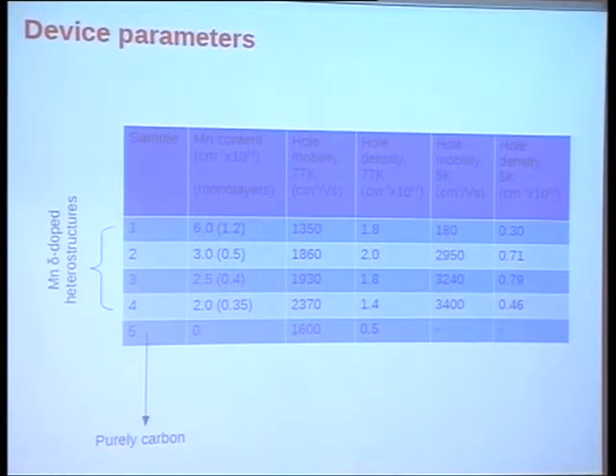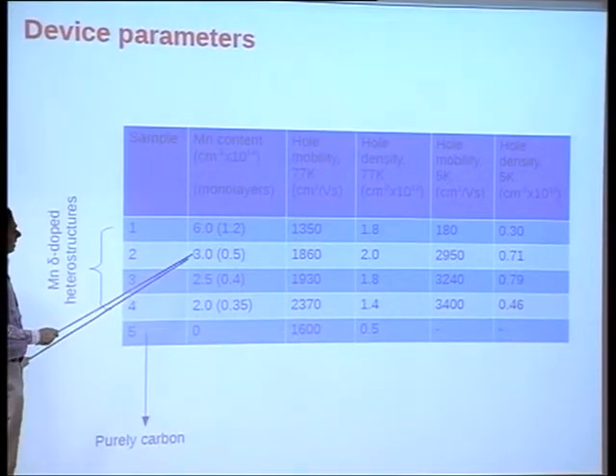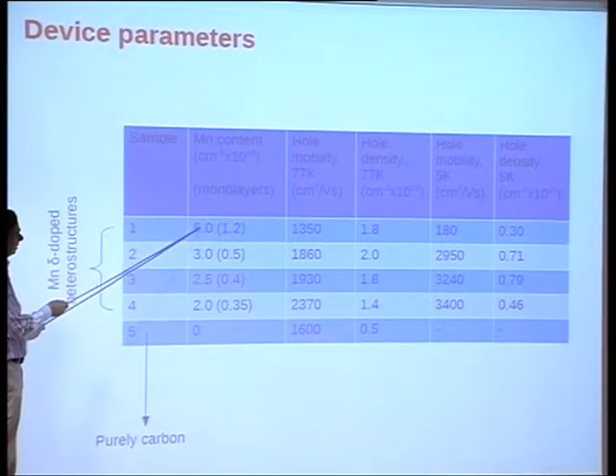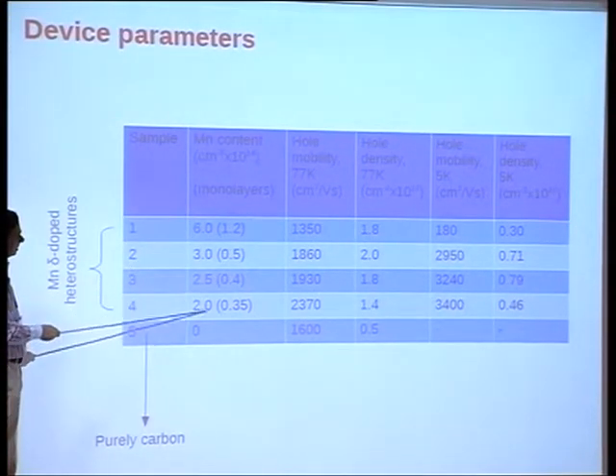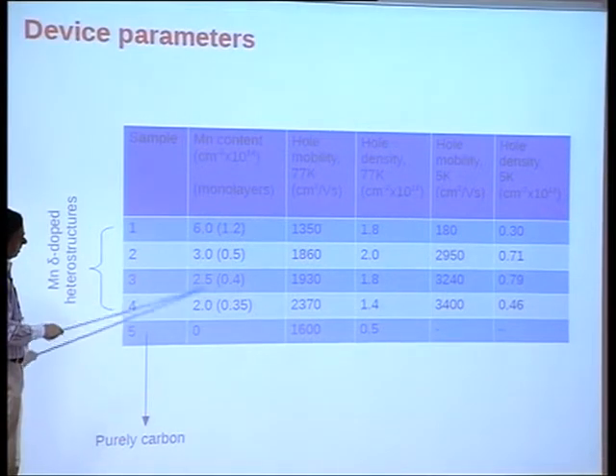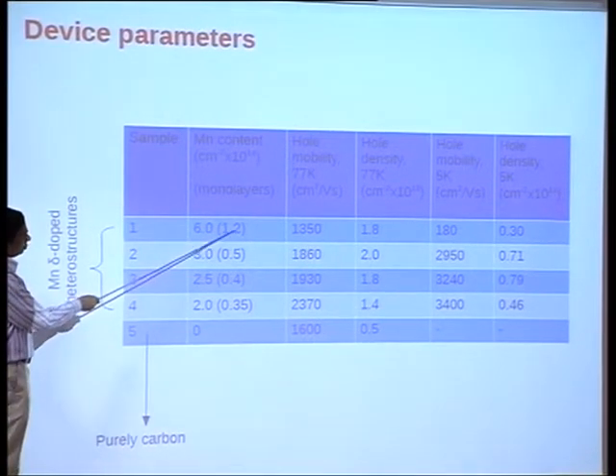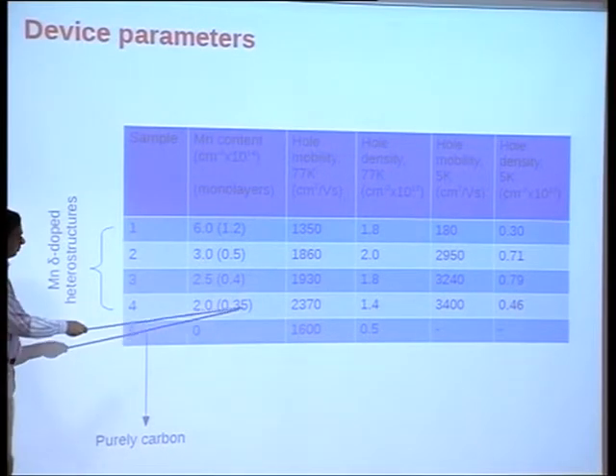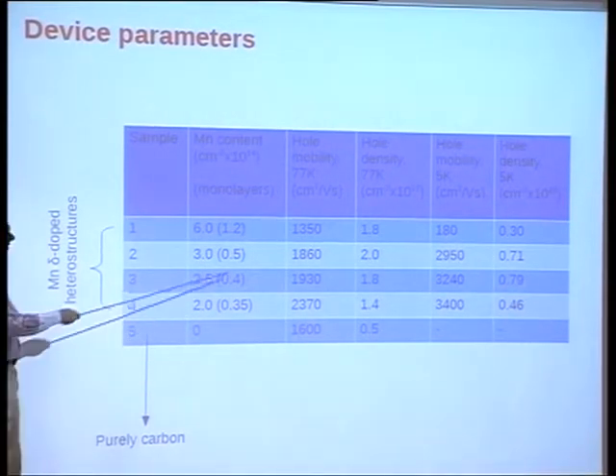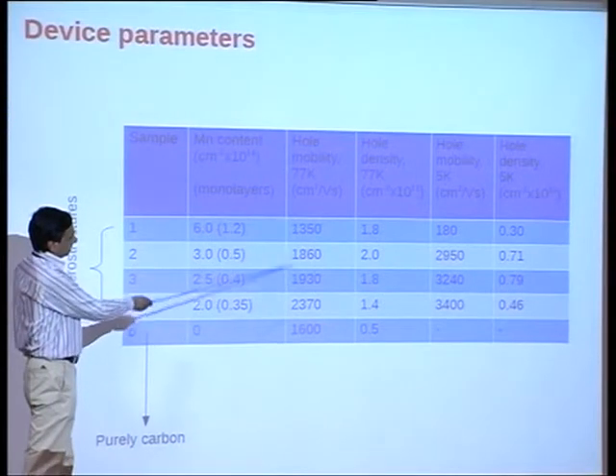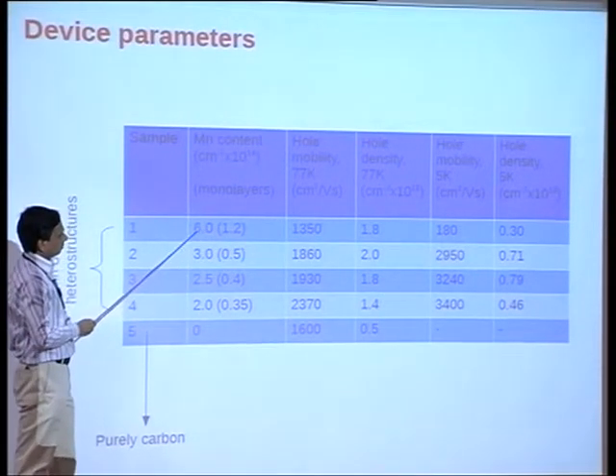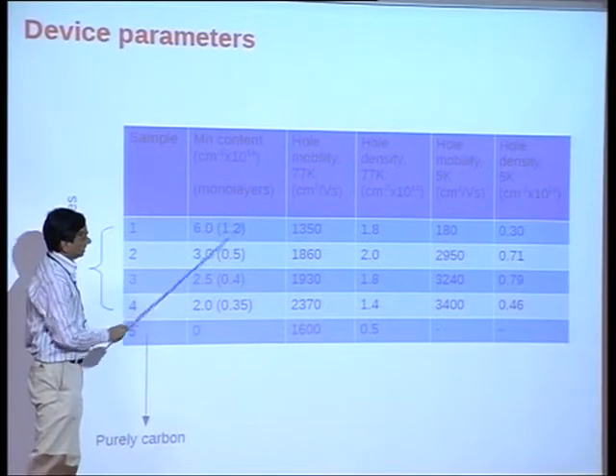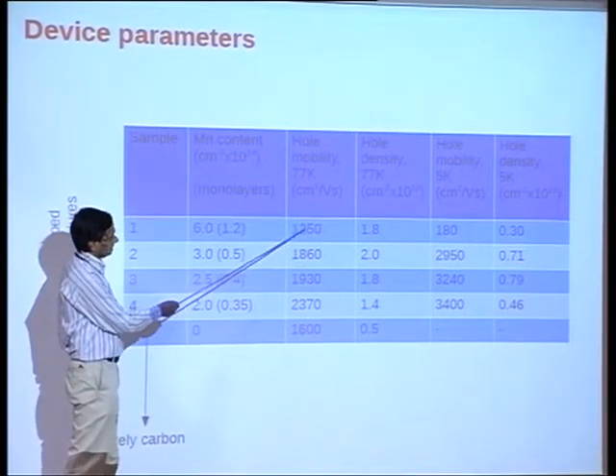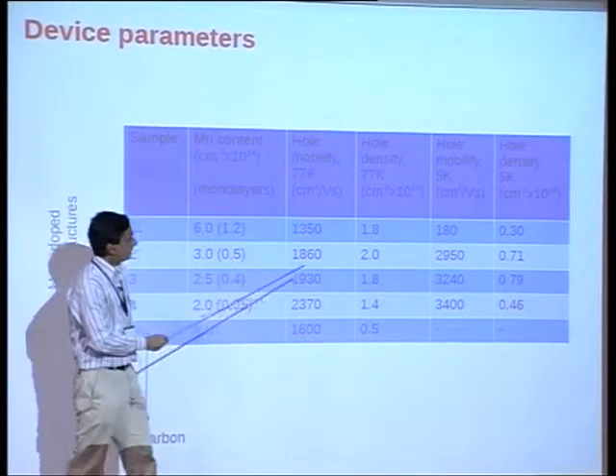Okay, so here are some of the devices generated by my collaborators. These are delta dopings of manganese through a considerable range, from 1.2 monolayers to a third of a monolayer. And the mobility correspondingly varies quite a lot. It's low here because of heavy doping. The ionization of these results in more scattering centers, and therefore you have lower mobilities.